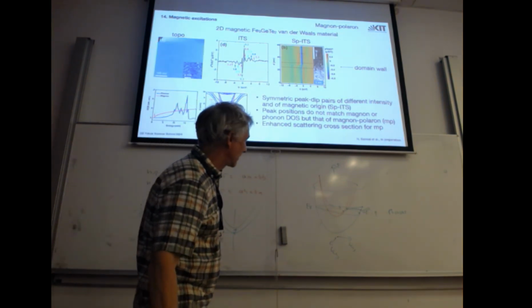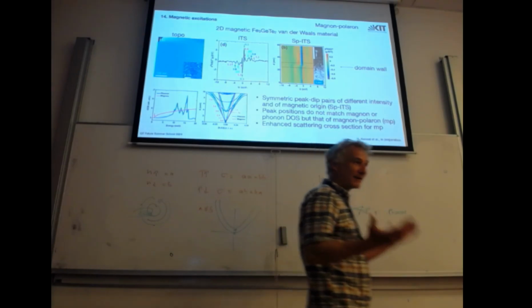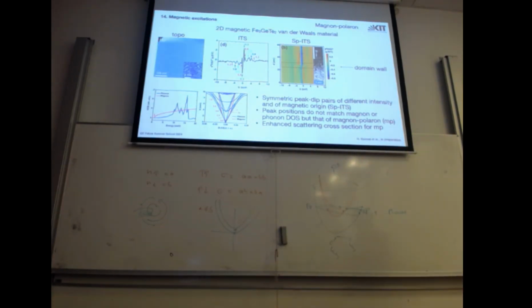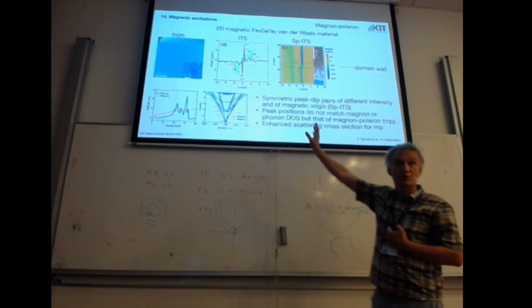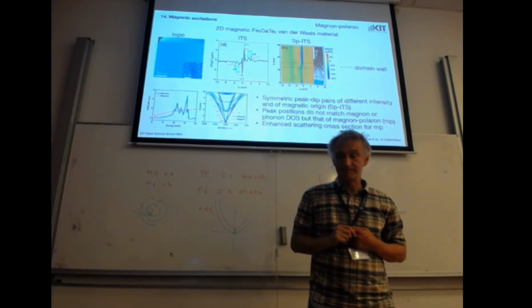So we have phonons and magnons, but if you distort the lattice, if there's magnetoelastic coupling, you will also change the direction of the spin. So distortion of the lattice changes the local anisotropy, and you can tilt the spin. So that means there's a hybridization happening between magnons and phonons. If the energy and momentum match, there is a forbidden crossing.